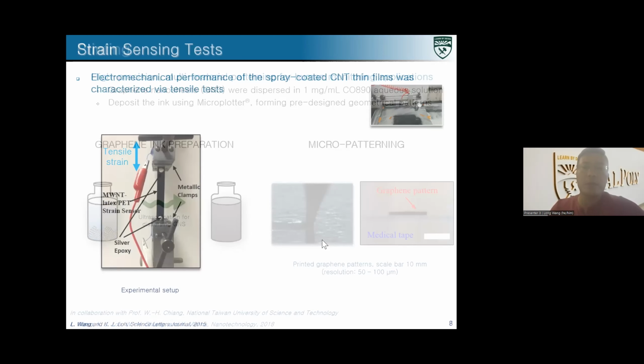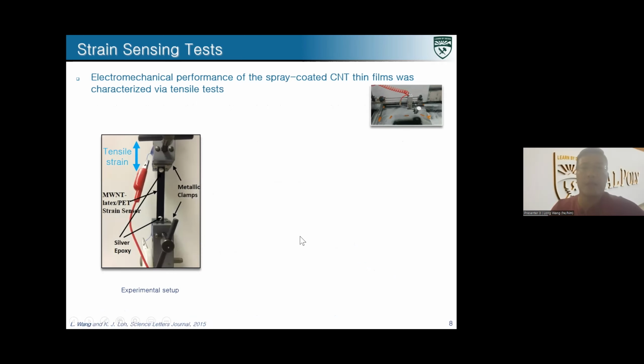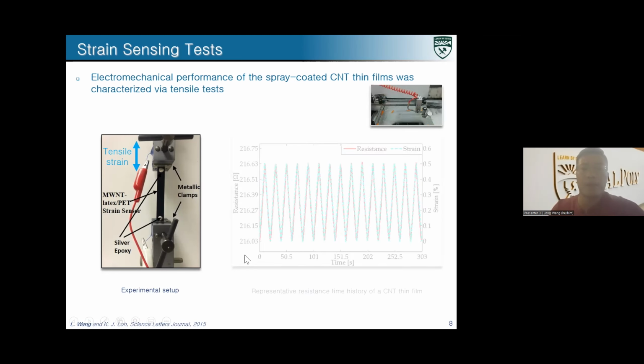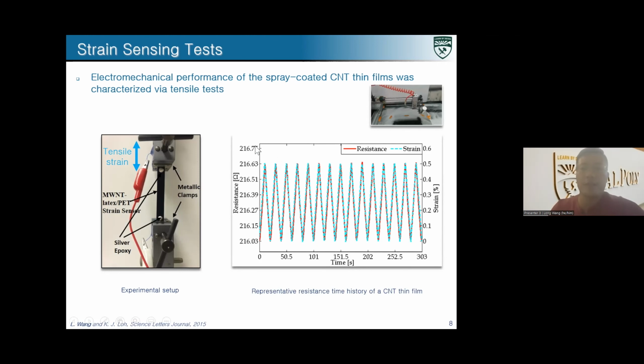So moving on, once we manufacture the material, like I said, we have to characterize its sensing property. We are interested in the strain sensing property, and we conduct electromechanical testing. Essentially, we apply mechanical load on the material and simultaneously measure the electrical property of those materials. This figure shows some of the results we have: the electrical resistance is represented by the red line, which is in accordance with the applied strain, shown in the dashed line. This basically indicates that our material can be used for measuring strains.